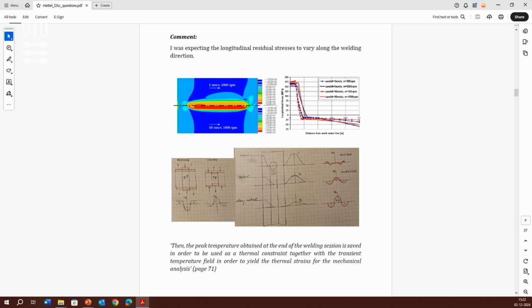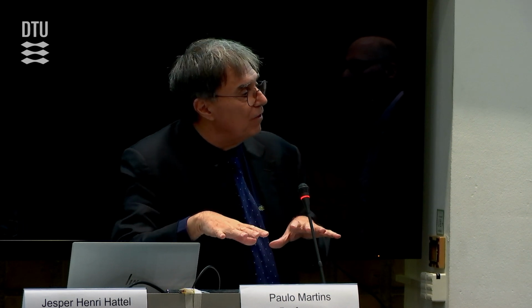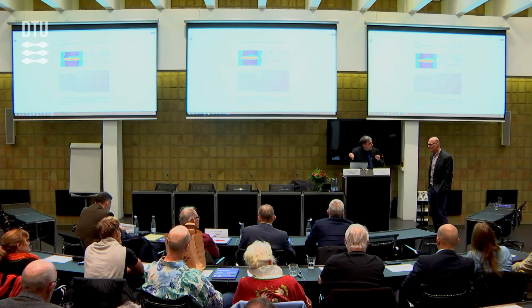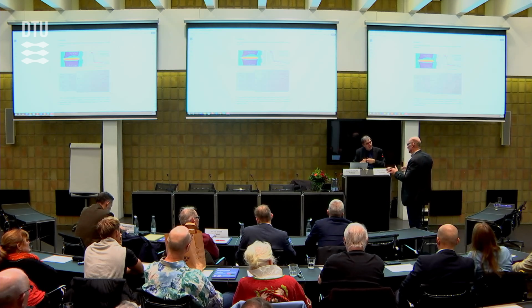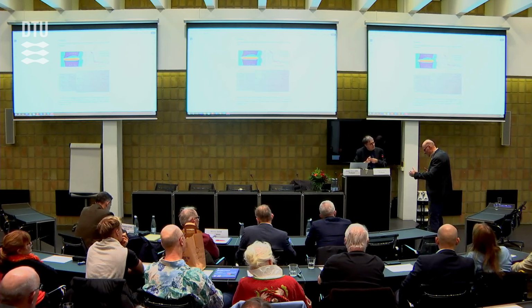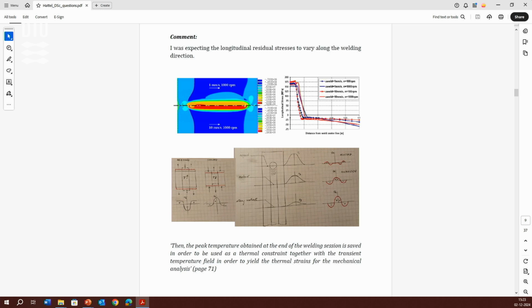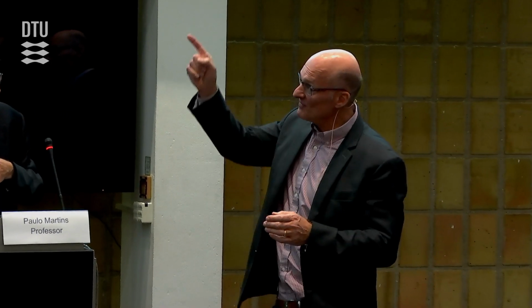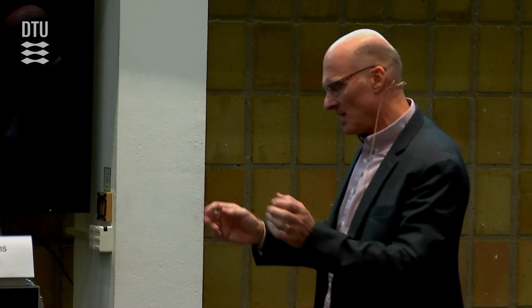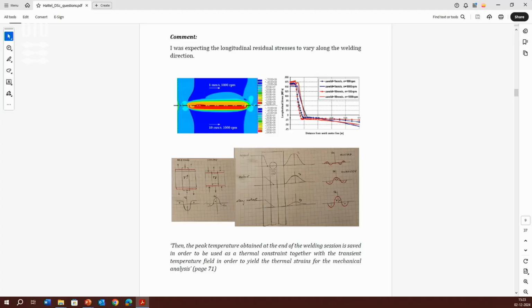right? Unloading residual stress is just at the end of the thermal calculation, or do you do thermal stresses during the heat source movement? Well, it's a sequentially coupled model in the sense that you calculate temperatures and you calculate the thermomechanical or the mechanical problem in which you solve the equilibrium equations, you get displacement, strains, and stresses, right? So there is no coupling back from this simple model. In this simple model, the temperatures are not depending on the mechanical solution. But it's, of course, a transient. I mean, it's a quasi-steady state in the sense that you send results from the thermal calculation into the mechanical calculation, and you go like this in time, and then you get these results, you could say.